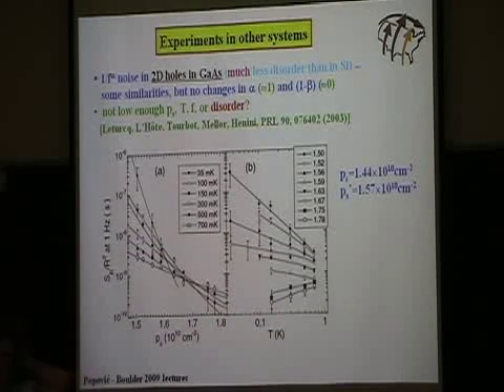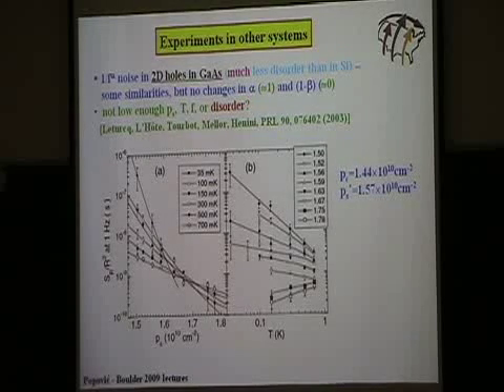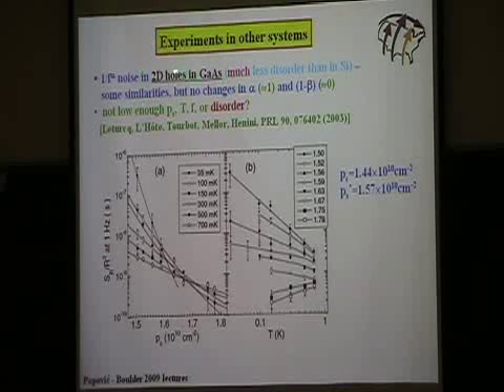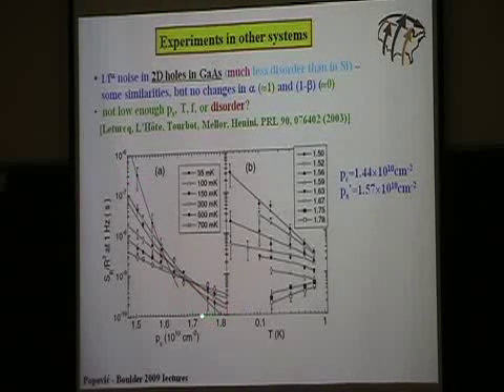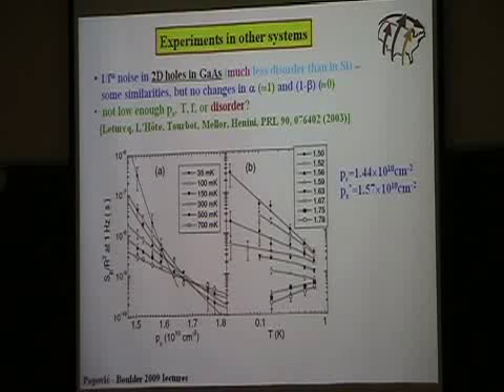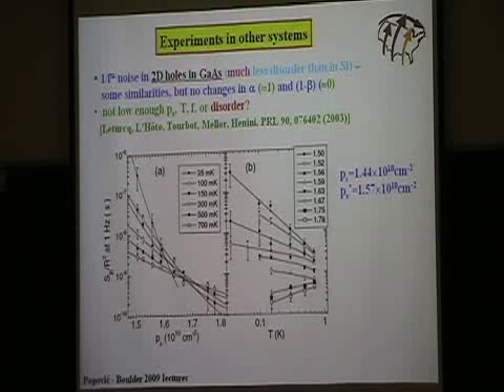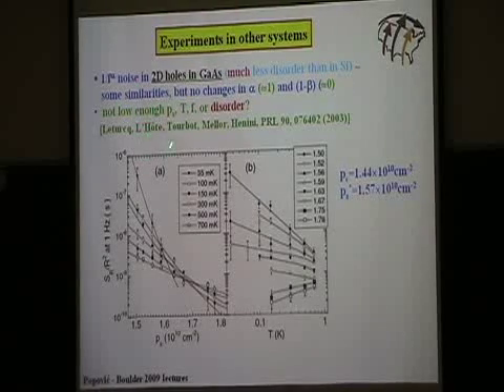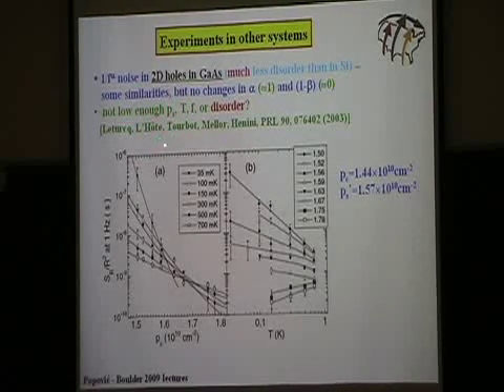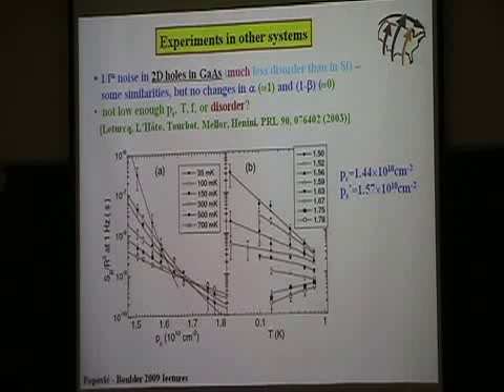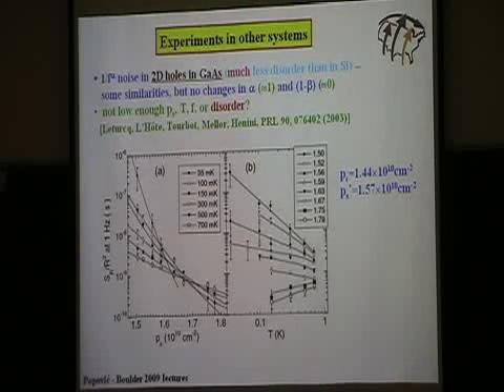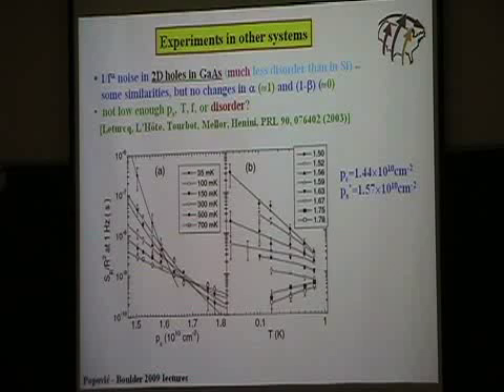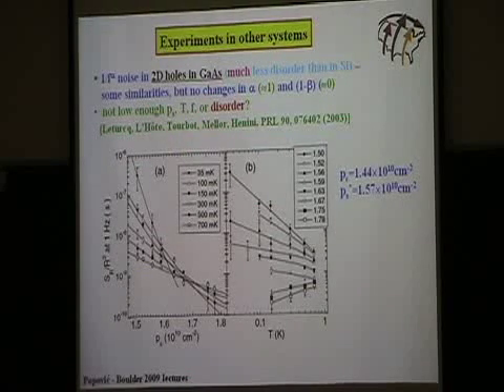Now, what about experiments in other systems? Somebody asked about this. This group, also at Saclay, tried to measure noise in a 2D hole system of gallium arsenide. They did find some increase of noise as the hole concentration was reduced and the temperature was reduced, but they did not find any evidence for glassiness similar to what we have found. Now, we could say maybe they didn't go to low enough densities, temperatures, frequencies, whatever. But I think it's more likely that the samples were too clean. There was simply not enough disorder. So one way to find out would be to look at this kind of system with more disorder. But guess what? As Michelle was saying, they've also stopped working on this. They're working on something else. So guess who will have to do this?